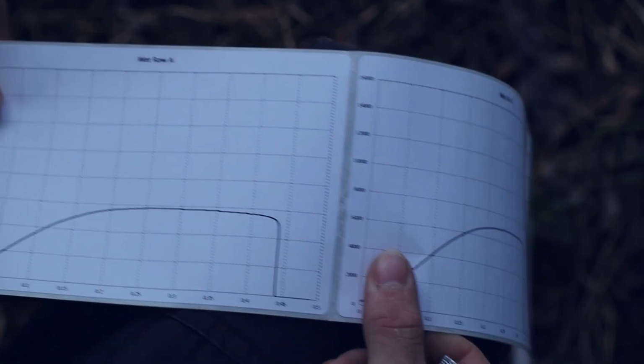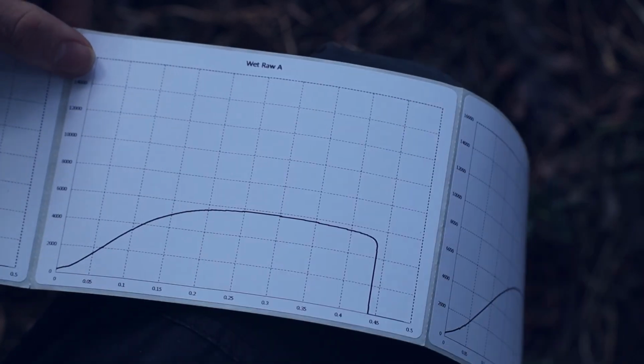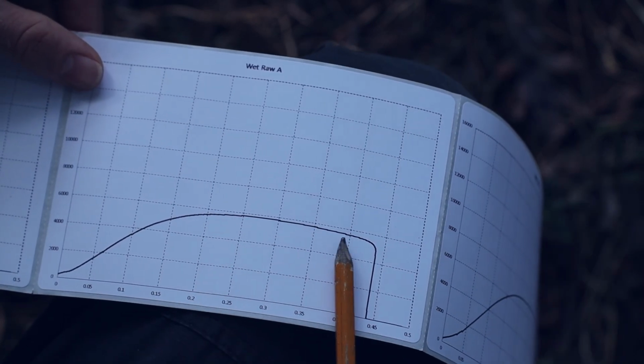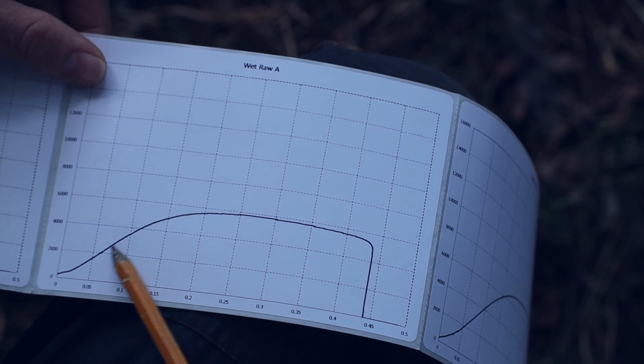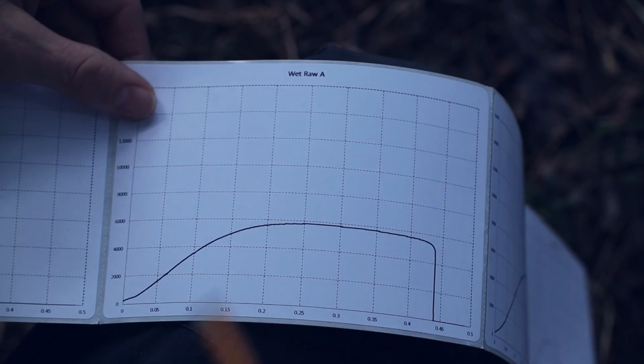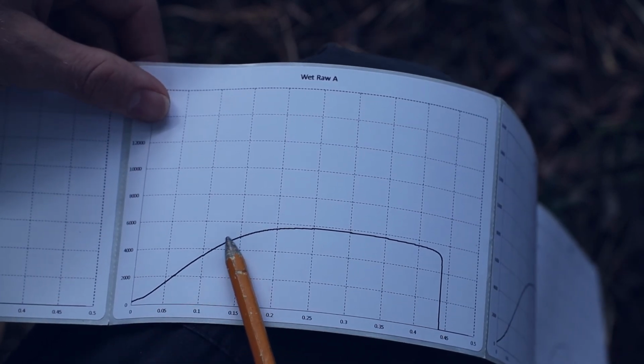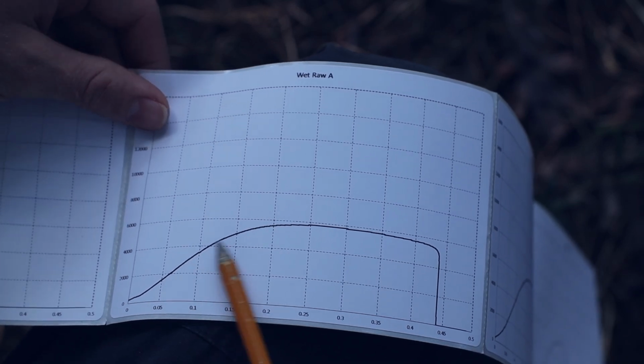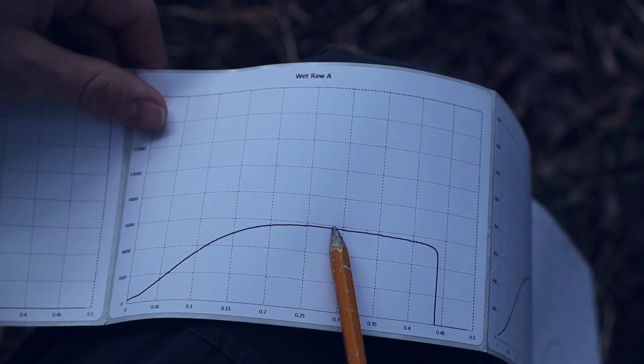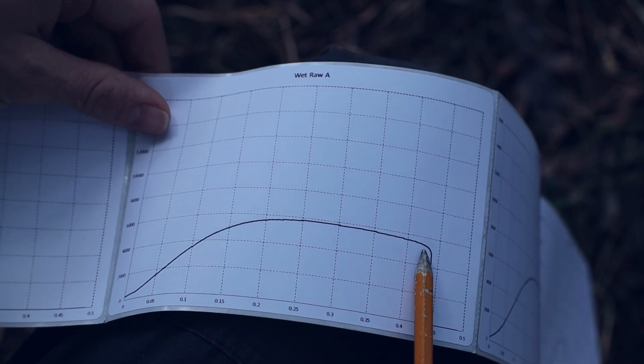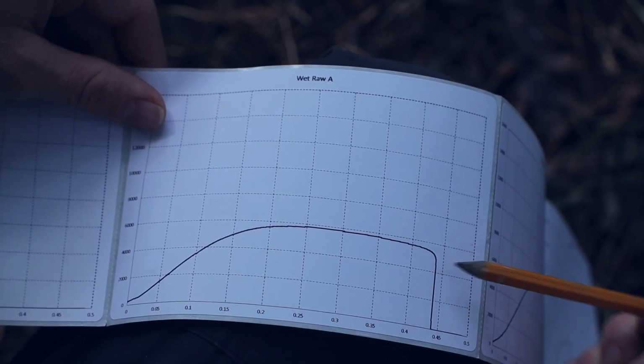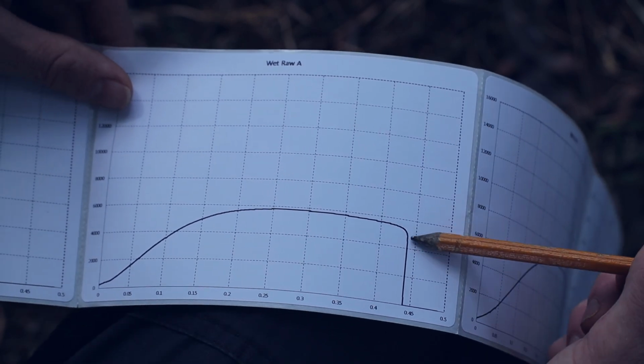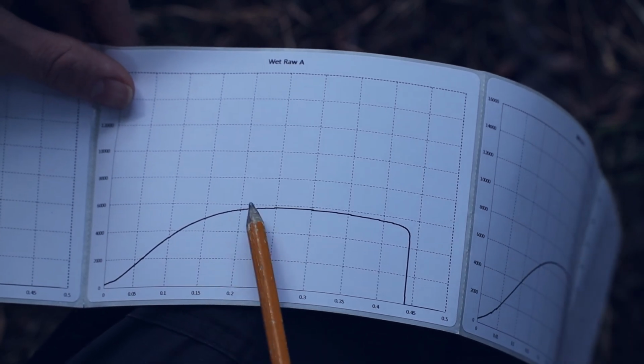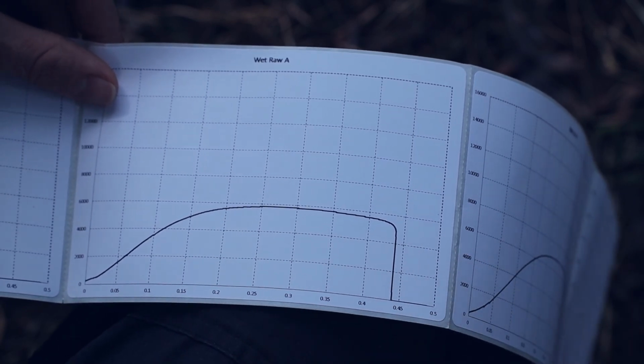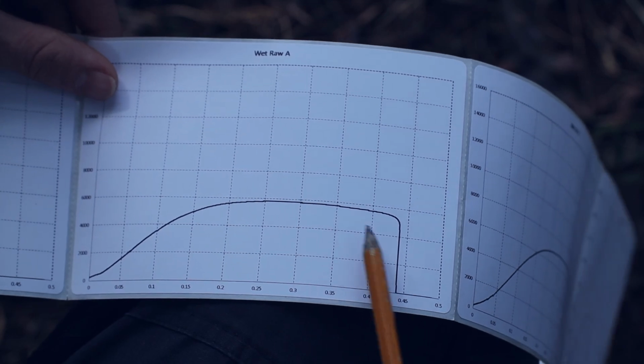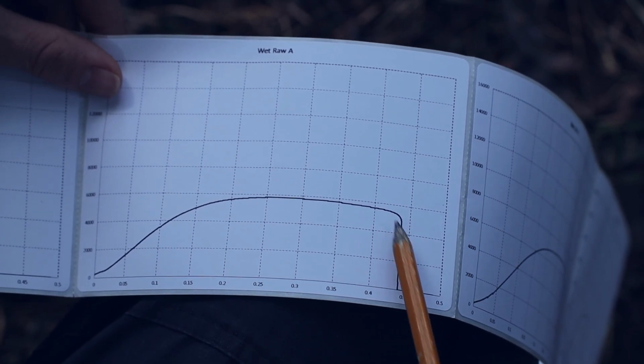Moving on to the wet samples, we have some pretty serious change. You can see obviously our ultimate tensile strength is way lower. We have a small region right here where we have elastic deformation. Very quickly we move into this long transition zone where we begin to have permanent deformation, but of necking, the sample actually necks a lot before finally tearing at the end and breaking. And this tear right here is due to the glass fibers in the nylon. If this was just a plain nylon, it would neck for a ridiculously long period of time before failing.